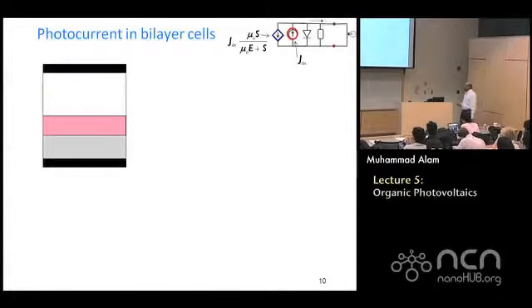Now, one thing you can see is that this is a little bit complicated. If an exciton is generated here, far away from the diffusion length of this junction, then all of them that have diffused here will self-recombine, because before they find this junction which will pull them apart, they are very close together. They will recombine, give up the photon or give up the energy, and that exciton is gone. That photon has no purpose whatsoever in this discussion. So the exciton diffusion length is square root of D tau x.